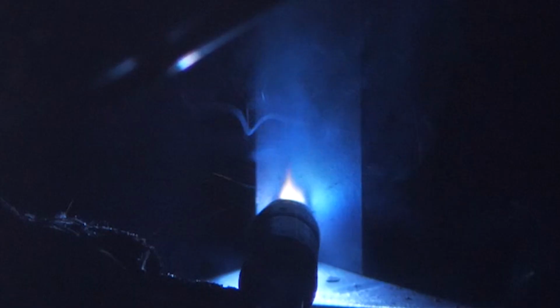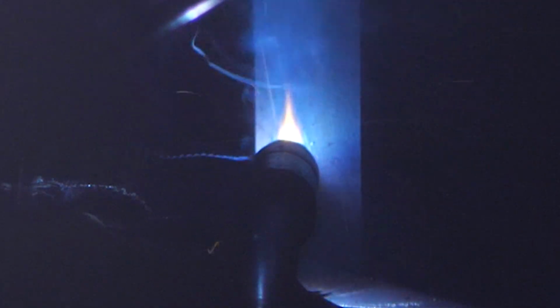All right, the MEGAFIL 713R. Right off the bat, I can tell the puddle is a lot more fluid. I do have the exact same parameters like I did with the 777, but definitely a much more consistent spray across the arc. I could tell for sure that the filler material and the slag are both just pinching down really nicely